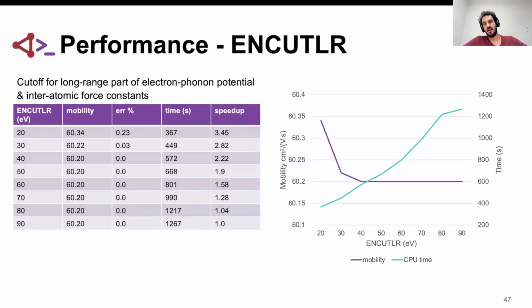Another INCAR tag is ENCUTLR, also a cutoff, but for the treatment of the long-range part. Again, the mobility doesn't change significantly — we are always below 1% error. You see that the computational time does increase significantly without much benefit to the accuracy of your calculation. So again, we should just use the lowest possible value of ENCUTLR that doesn't change the final value significantly.